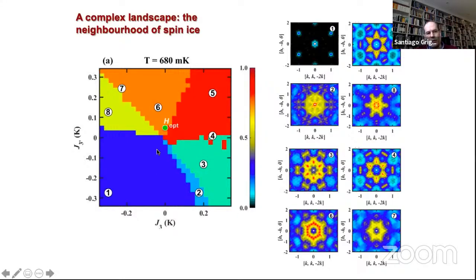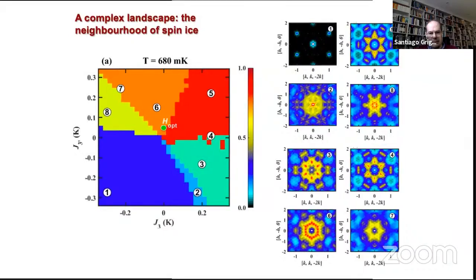And this is not altogether surprising, in the sense that, as we said from the very beginning, we're working on a frustrated system. So there are many forces that are being balanced. And as soon as you add external perturbations of some sort, for example, in this case, we're adding further neighbor interactions, even though they're small, they can make big changes in your system.